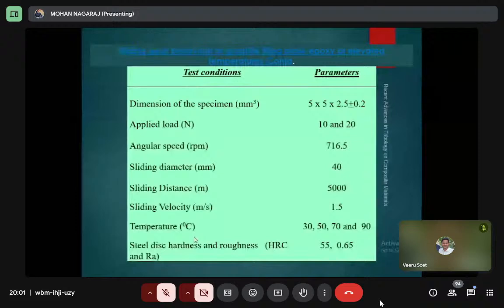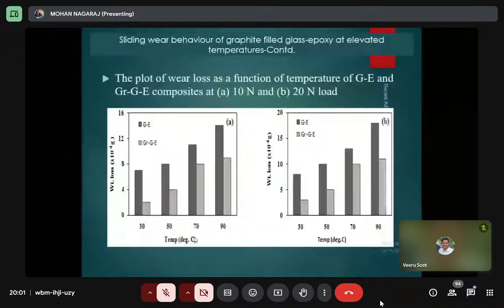So here the weight loss is checked at different temperatures for the polymer matrix composite. It gives very good wear resistance as compared to the general materials, because of the lubricant-like material, graphite, which enhances the wear properties of the materials and also gives very good tribological properties. Generally, this kind of material can be used in bearing liners instead of polytetrafluoroethylene, which is costly. Why are we using the filler materials? For cost reduction. Importing filler materials into the polymer matrix composite gives a cost reduction and also improves the mechanical and tribological properties.